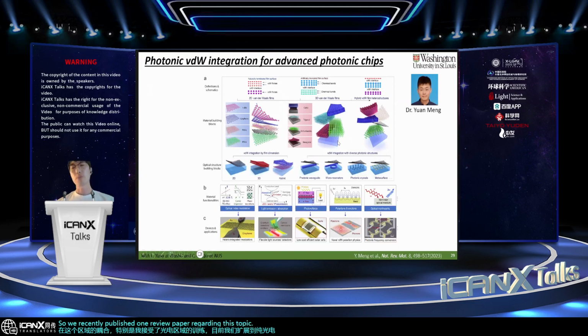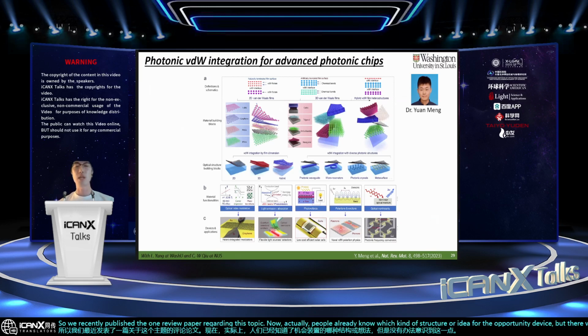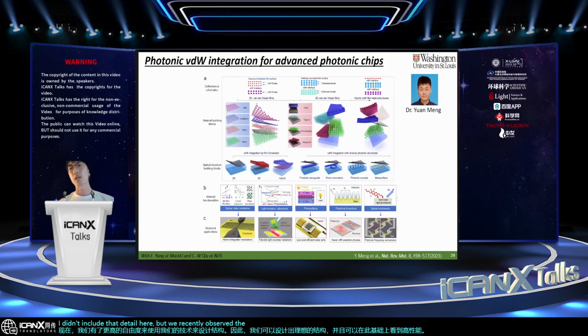Now, people already know which kind of structure is ideal for photonic devices, but there was no way to realize that photonic structure. Now we have much higher freedom to design that structure using our technique. So we can design the ideal structure and see high performance. Because of the time limit, I didn't include the detail here, but we recently observed extremely high electro-optical modulation based on this structure, especially 20 times better than the state of the art.